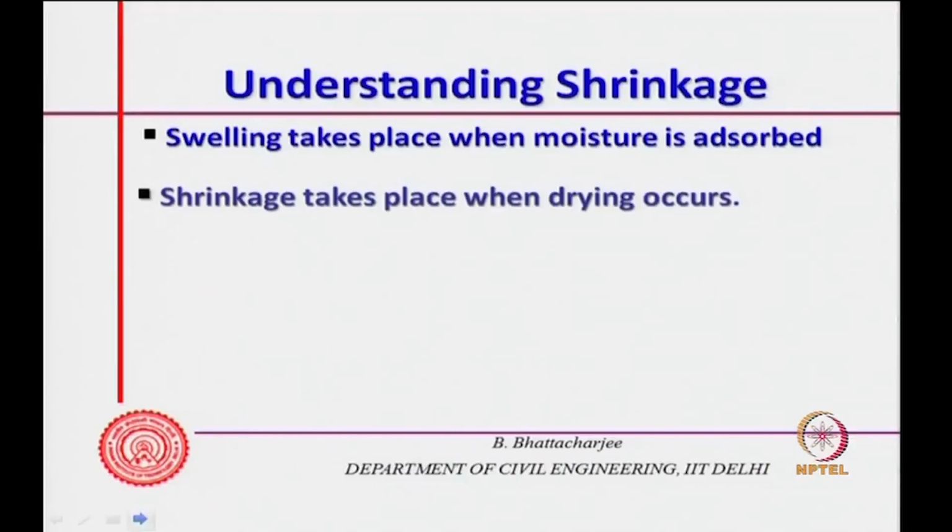So, when drying occurs, R will become smaller. As the moisture is withdrawn, R will become smaller, and the vapor pressure change would actually occur, and at this smaller R, the compressive forces that would be generated onto the skeleton would actually compress the system, right.